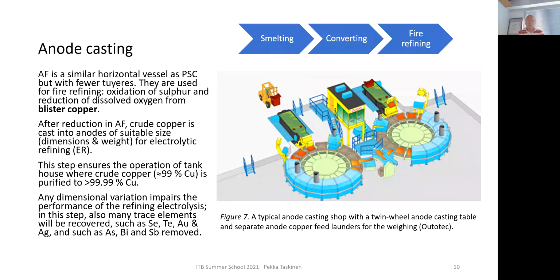So it's very pure material, and some of the impurities have also maximum concentrations allowed before it can be sold as standard grade copper cathode. Typically in Europe we call LME grade, A grade copper and cathodes, which have long list of elements, including bismuth, antimony, arsenic, with 1 ppm or 2 ppm of each, which are allowed,